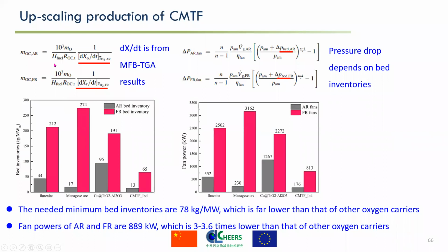Based on the reaction kinetics, we can evaluate the required bed inventory in the air reactor and fuel reactor. In these equations, the reaction rate is from the TGA results. Then, according to the bed inventory, we can calculate the bed pressure drop. As we know, the fan needs to overcome the pressure drop in the fuel reactor and the air reactor, so we can calculate the fan power by the equations. We can see the results.